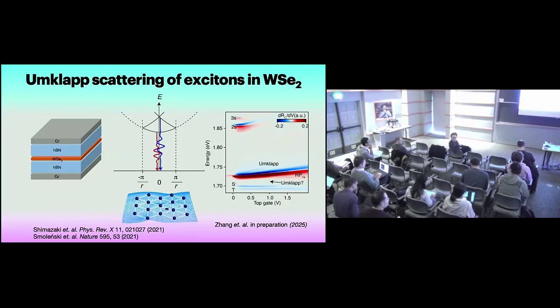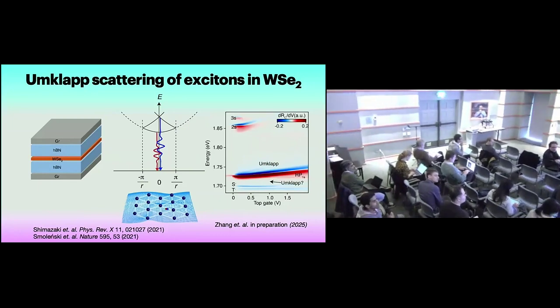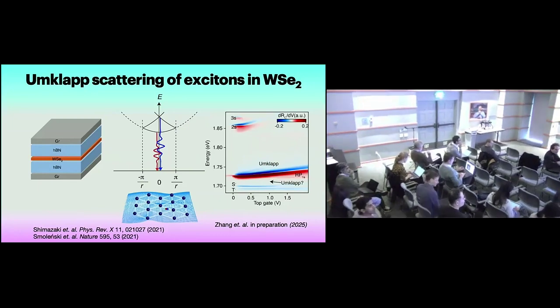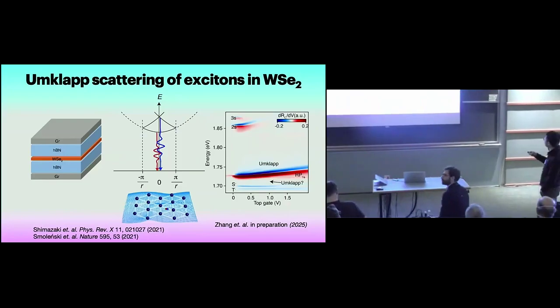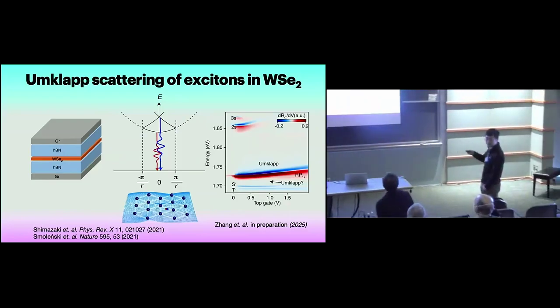This is a basic question. Experimentally, how do we know that it's Umklapp scattering? The other signal is from Umklapp scattering. Yeah. So these features are very strong, right? So you can see them at all different temperatures. You can see them across all kinds of samples. This Umklapp feature only shows up at a low temperature, at a low density, and also only in some materials, like in some samples, which is very clean. So it doesn't show up in all materials.